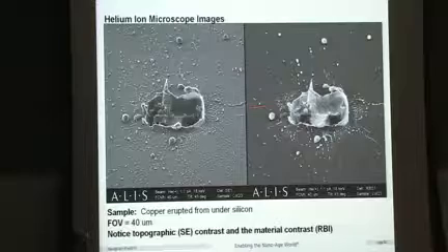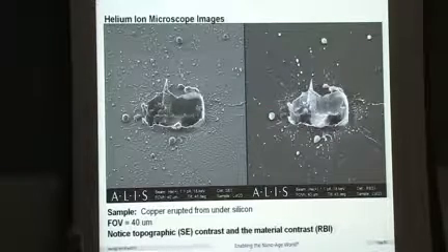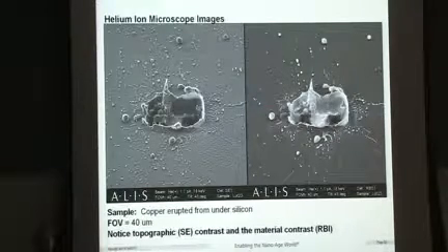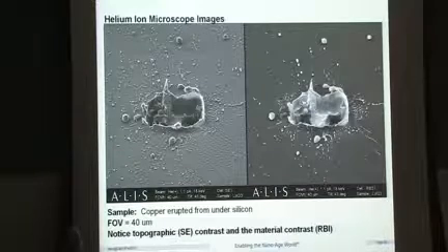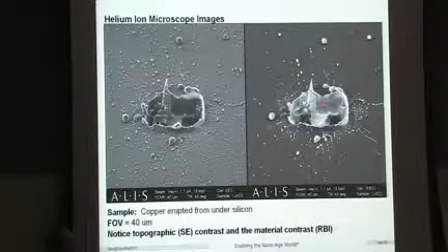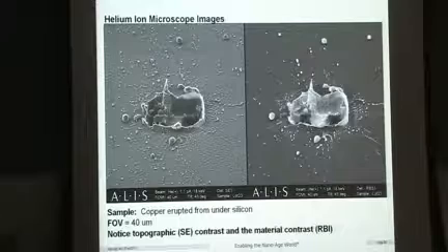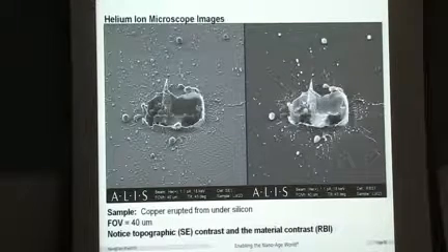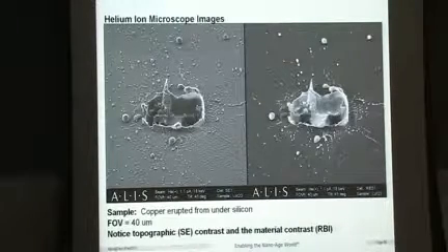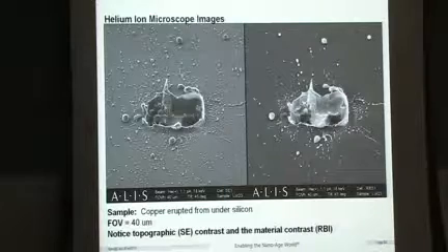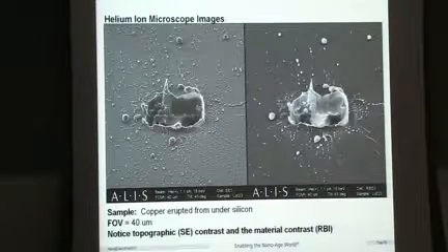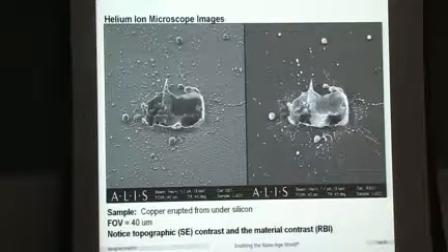But when we switch over to backscattered helium mode, I mentioned the cross-section of scattering of helium goes as the atomic number. So right away you can tell I'm looking at copper here and silicon here. You can now easily distinguish these different materials. So it's a nice, more or less orthogonal imaging mode that you can jump to quite easily. And you can even image simultaneously with these two different imaging modes.